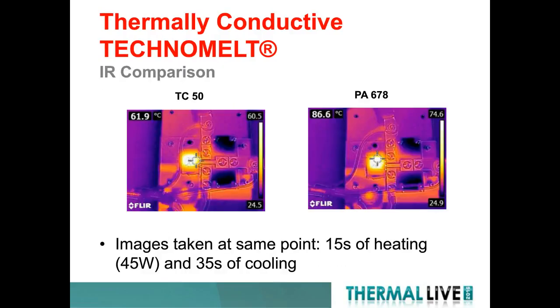We grabbed some images with an IR camera as well. These images were taken at the same point: 15 seconds of heating at 45 watts and 35 seconds of cooling, so into that cooling curve itself. After they heated up, we let them cool, and 35 seconds later captured an image.